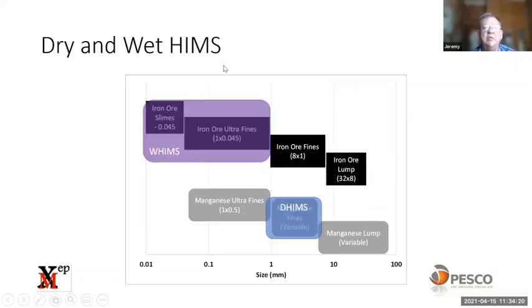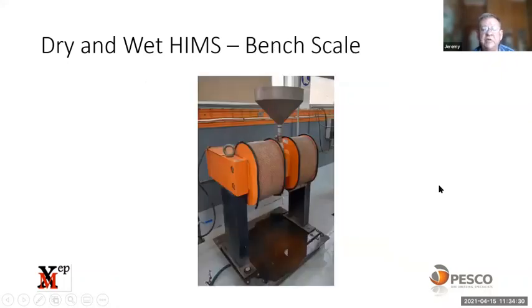If we look at dry and wet high intensity magnetic separation, that covers the manganese fines, as well as the iron ore ultrafines and slimes. Bench scale, you have a little unit like that. So you add the sample through there, you can adjust the field strength. So you can do it at 7,000, 8, 10, 11, 12, up to 15. And then your magnetic particles get held back and your non-magnetics go through. And so by adjusting the Gauss setting, you can work out how much is recoverable. And then you analyze the products for the grade.